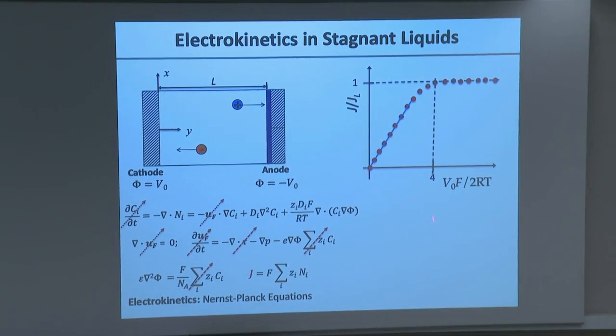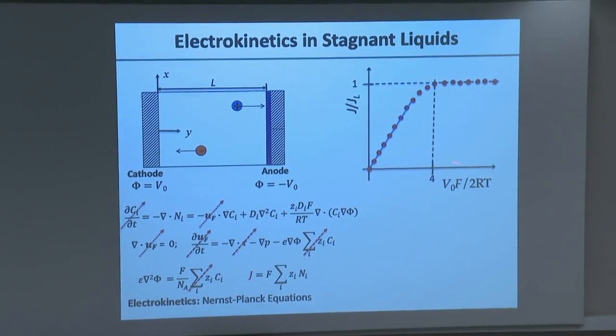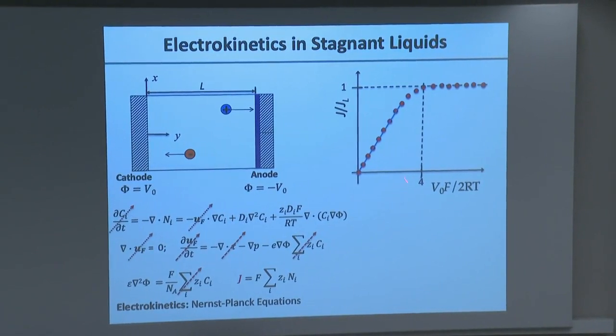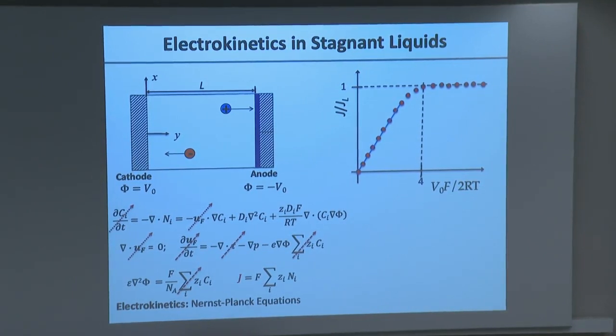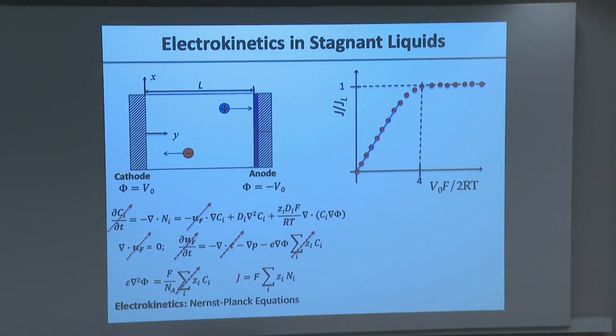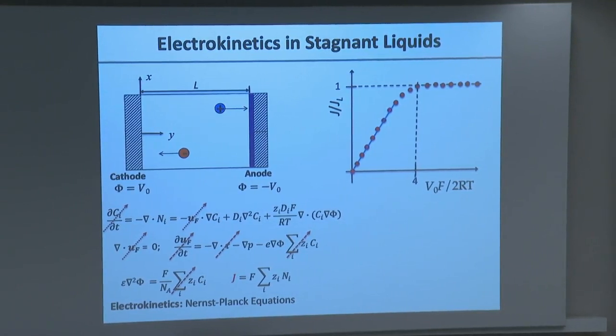But when you get above a dimensionless potential of order 4, you notice the current saturates at a certain value such that this ratio, J over J_L, is 1. And that value is called the diffusion limit. This is where J becomes J_L, the so-called limiting current. So it's telling you that in an electrochemical cell, there's a maximum current that you can operate at. Once you get to that maximum current, it doesn't matter how hard you drive the system, you can't get any more current out of this system. That's what these equations tell us.